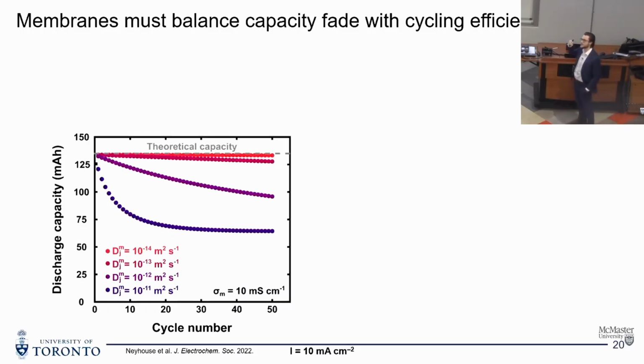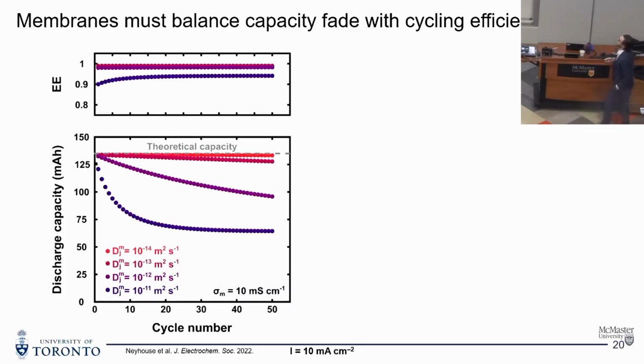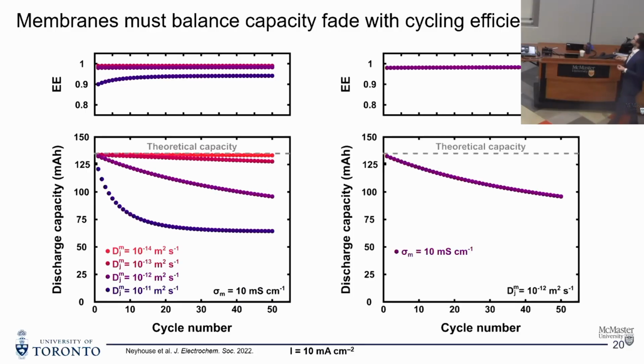So this would correspond to a very selective membrane that would perform well. And we can similarly look at the energy efficiency, where in terms of our penalties on energy efficiency, once we overcome a minimum low threshold of this diffusion coefficient, the energy efficiency becomes pretty high in general. Now, this is at a fixed membrane conductivity. I talked about the conductivity-selectivity trade-offs. If we instead fix the diffusion coefficient and vary the conductivity, here the light purple on the left is the same data on the right, just to orient you around that.